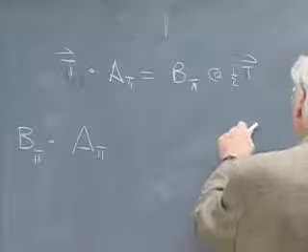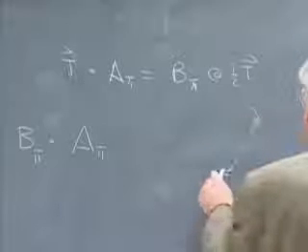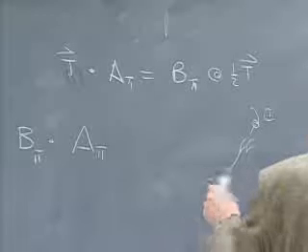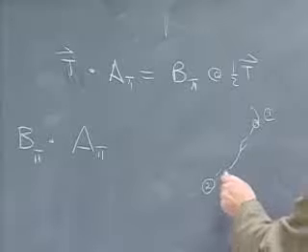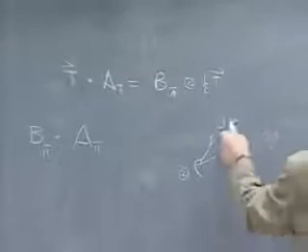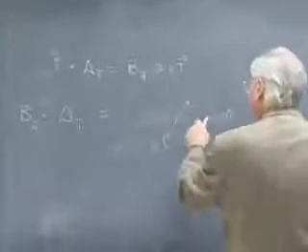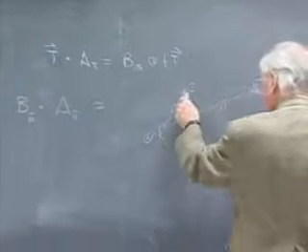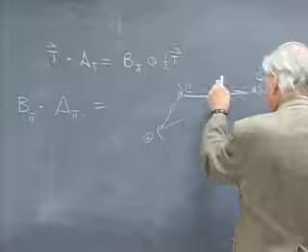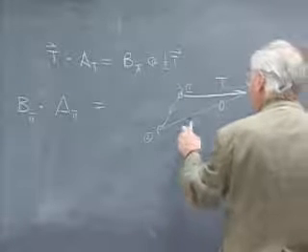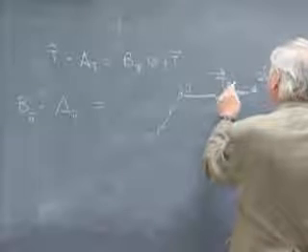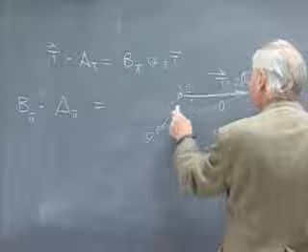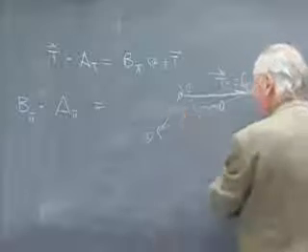Let's say there's a 2-fold axis here that takes motif number 1 and moves it to number 2. And then here is a second twofold axis, and this takes number 2, rotates it over here to number 3. How is number 1 related to 3? But in terms of this first theorem, not surprisingly, we have introduced a translation into the space which is equal to twice the spacing between the twofold axes, which I'll label as delta.